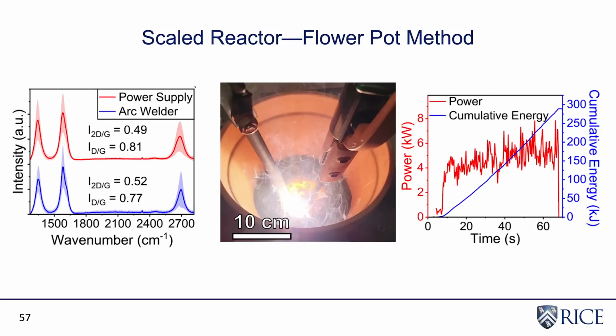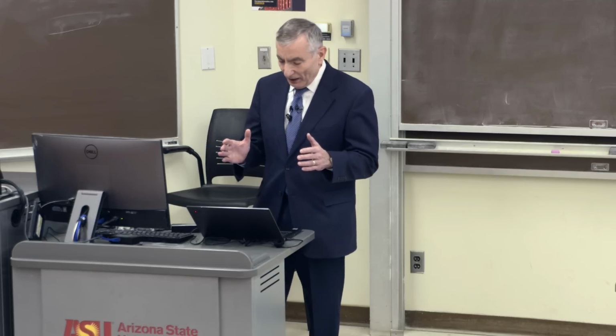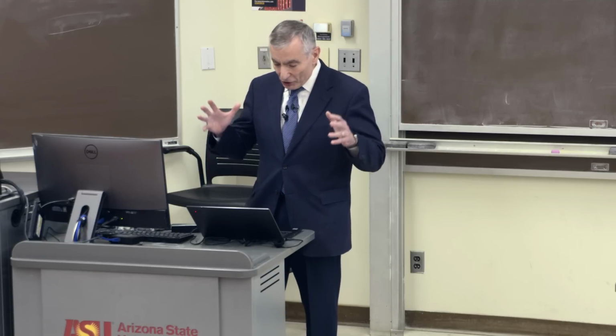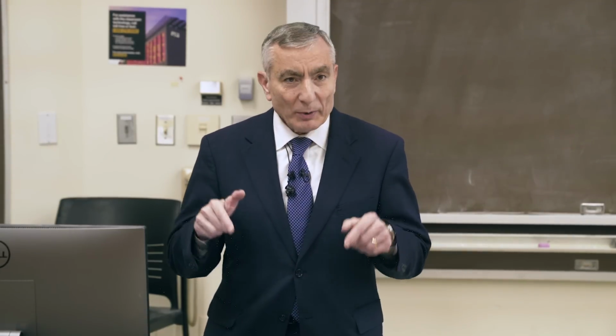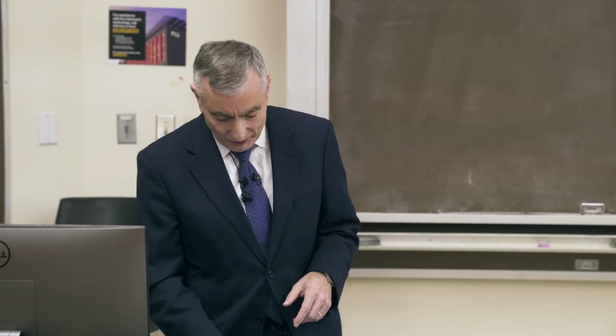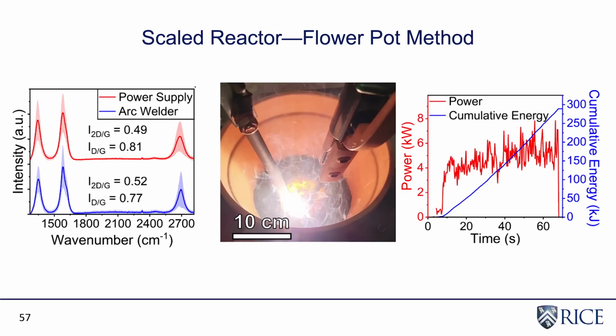You just go and you buy a flower pot. Flower pot is made out of clay, and so it can handle these temperatures. You just take metallurgical coke, put it in there. Metallurgical coke is $150 per ton. 2 carbon electrodes and an arc welder, and you get graphene. That's all it takes. Just do this in the hood, and the fumes are just blowing right out the hood.